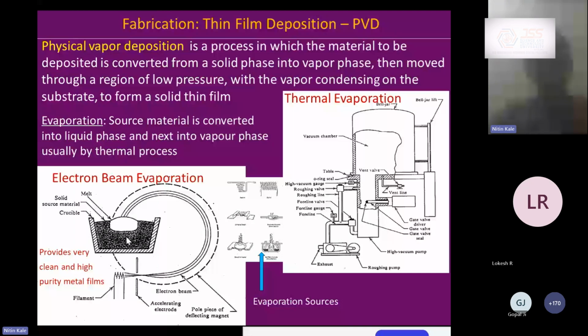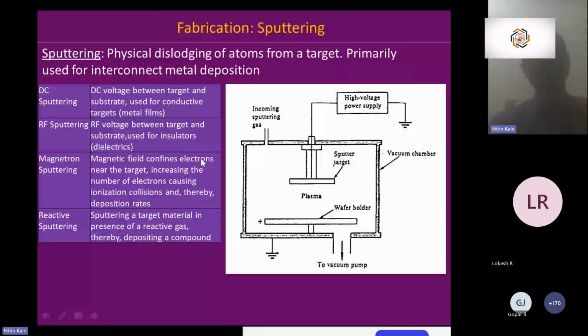Sputtering is another very interesting method of doing physical vapor deposition, where basically you have again a plasma and you have your source material, which is one of the electrodes, and the incoming gas is accelerated using the electric field, and it is made to strike one of the electrodes, which is holding, let's say you want to do gold deposition, so gold is your target. So it hits the target, it ejects out the gold material, and this material is then going to go and sit on your substrate. So you have various methods of sputtering. Magnetron sputtering is the most popular.